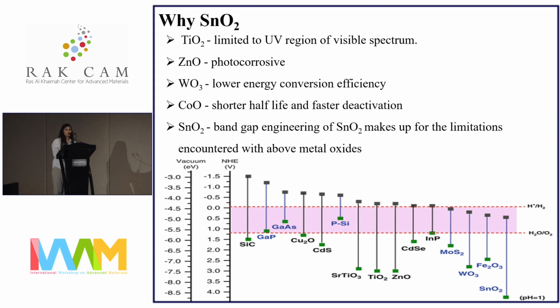So, the most essential requirement for a semiconductor to behave as a catalyst for photocatalytic water splitting is that the valence band of the semiconductor must be more positive than the oxidation potential of water to generate oxygen gas, and the conduction band must be more negative than the reduction potential of water to generate hydrogen gas.